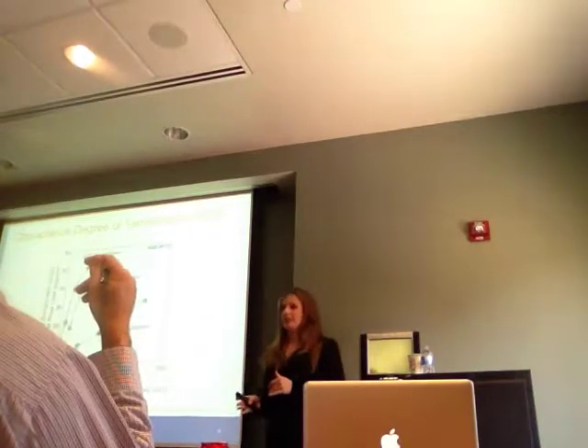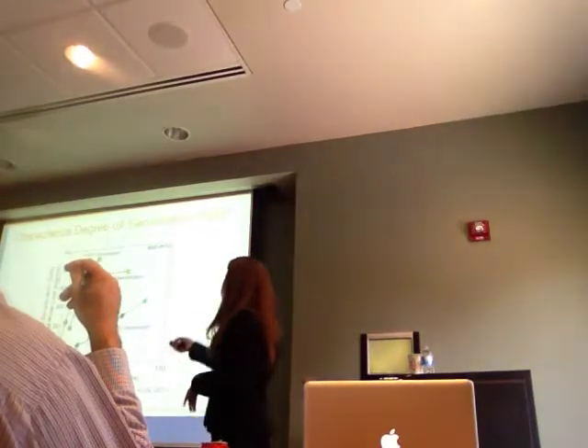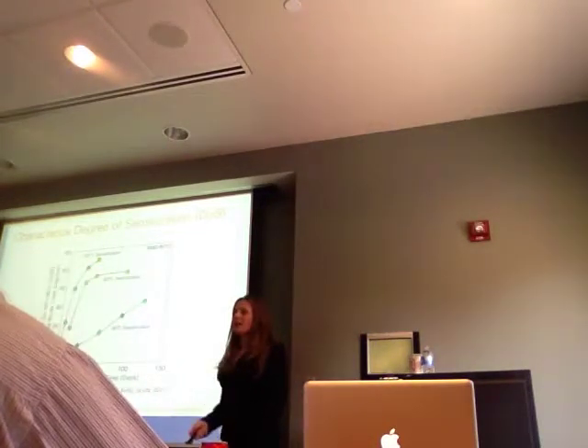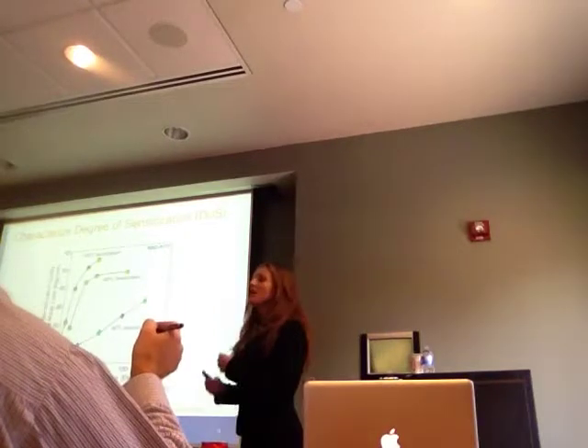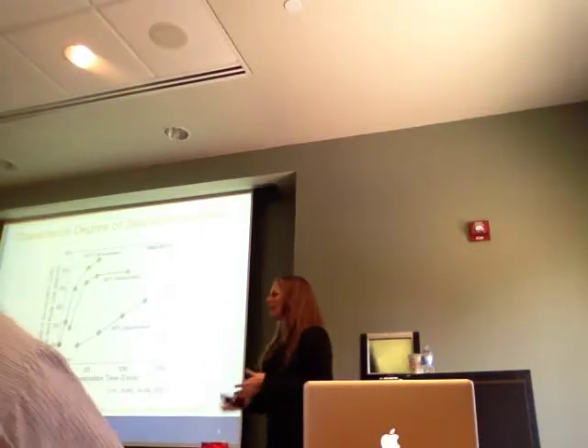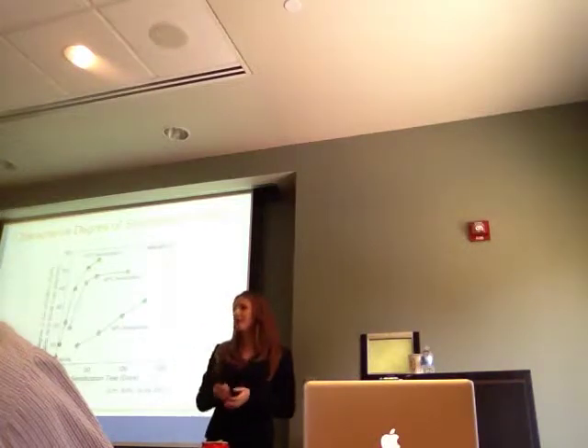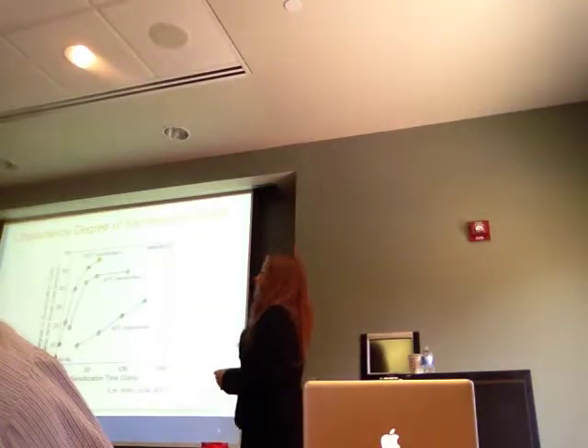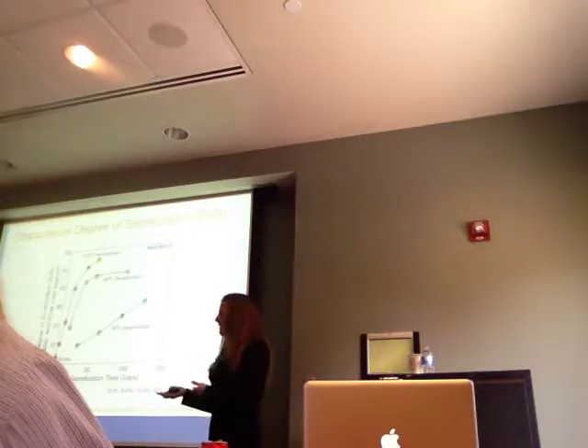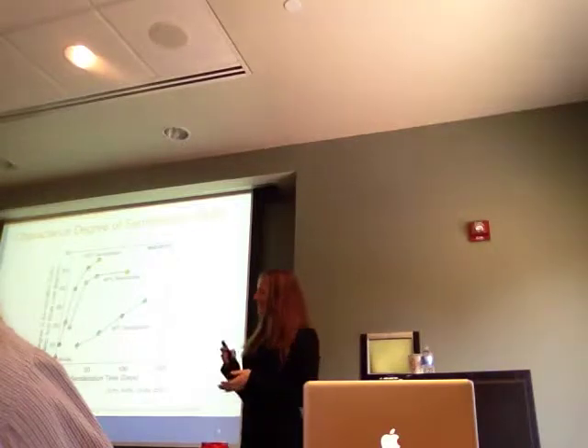So the first thing that we need to do is characterize this degree of sensitization, or this DOS level. And to do that, we use this nitric acid mass loss test. This mass loss test is ASTM G67, and what we do is we throw a piece of 5083 or an aluminum magnesium alloy into nitric acid and let it sit there for 24 hours. Then we take that piece out and we measure how much mass was lost. Nitric acid preferentially dissolves beta phase. So the mass loss can be attributed to the beta phase that was in your microstructure.